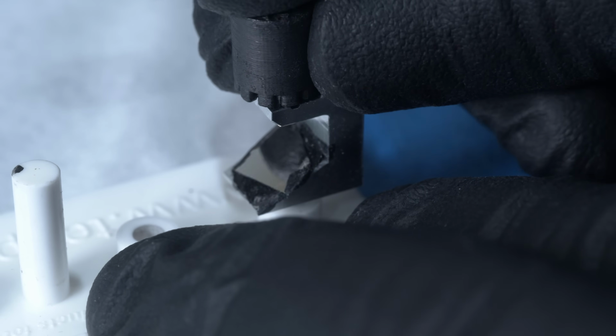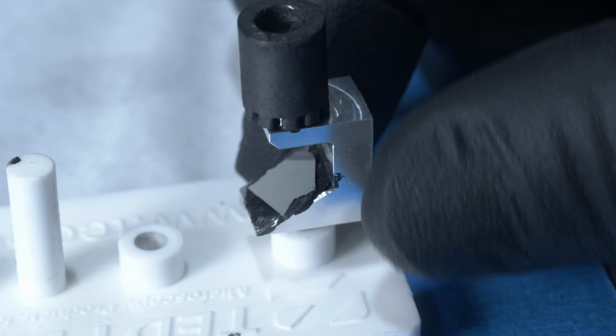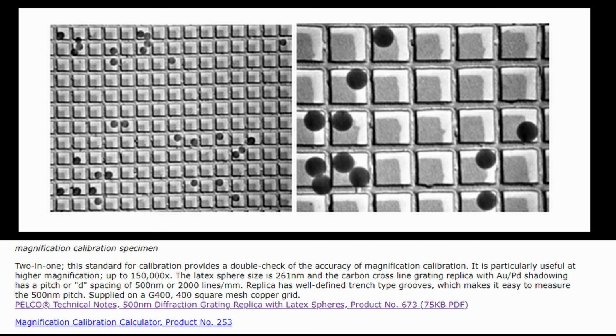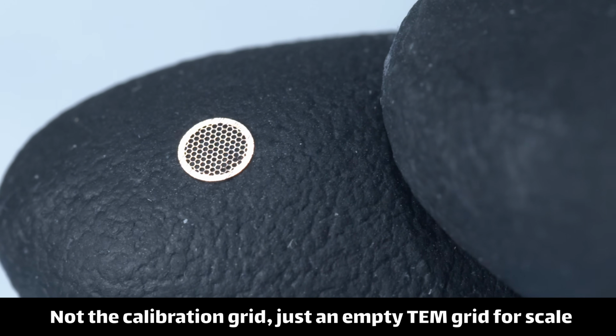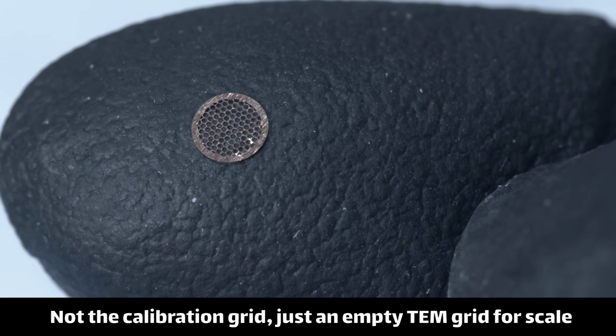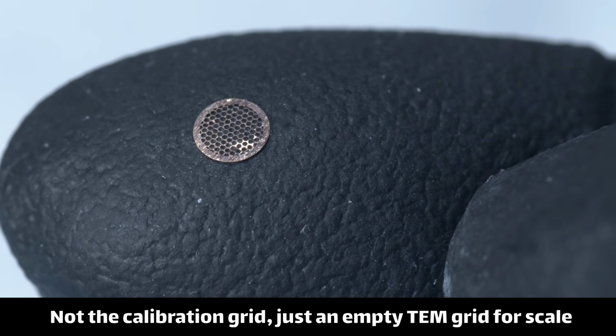Now, I wasn't really sure what to expect. I've never used a device like this before. So I ordered a test grid. This is a diffraction grating with 500 nanometer spacing and latex spheres placed kind of randomly on top of the grid. The spheres are 261 nanometers.